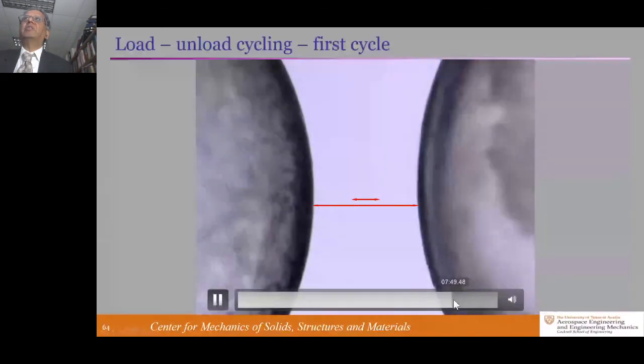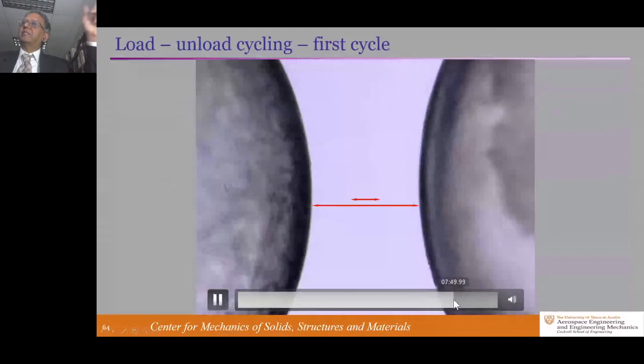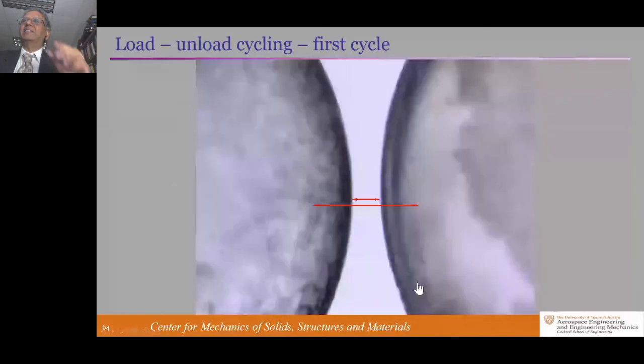More than that. We reload it to the same place where it was before, where the cavity from the right-hand side had popped. It hasn't grown. If you go even further there, it pops, but this time from the other side. So the first cavity that formed was healed. Not only was it healed, it was healed to be stronger than what it was originally. Interesting thing to talk about, and Oscar and I have been figuring out or arguing how to make this thing work. We've done a number of cycles of loading and unloading. Each time it seems to get stronger, but with some kind of a saturation. So we're dealing with statistics of defects that are nucleating these cavities, and there's a large problem to be explored here further. All right, with that, I'm going to close.